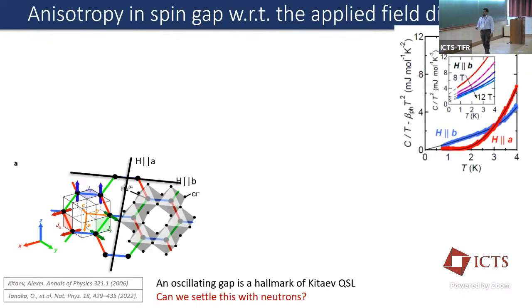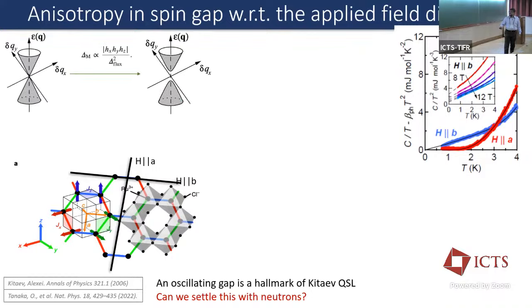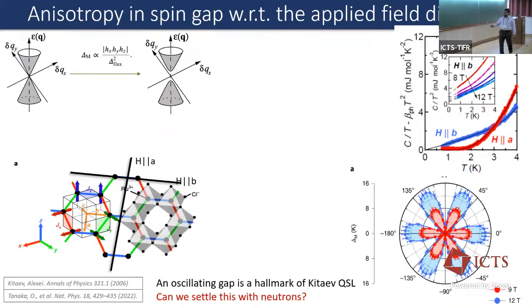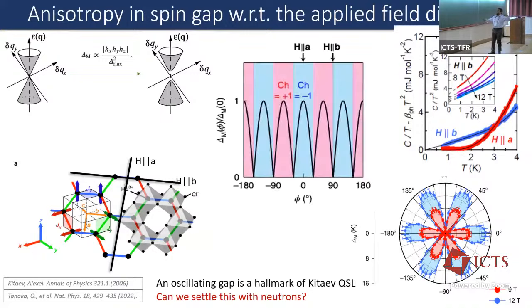There are also these new results on the heat capacity data, also I think from a very similar group, by Tanaka, which was published in Nature Physics this year, where they looked at the gap as a function of in-plane field directions in the sample. What they find is that for certain in-plane field directions, you see a gap. So along H parallel to A, you see a gap. And then when you have H parallel to B, which are those white...